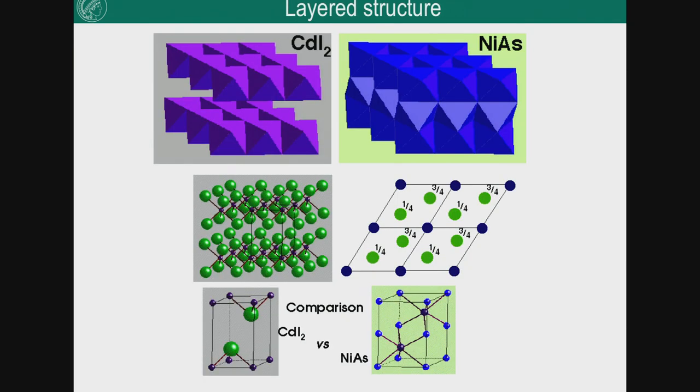So for example, I said if you have a hexagonal close packed lattice filled with all the octahedral sites with nickel, you come to the nickel arsenide structure. But if you remove one layer of nickel, so this would be Ni2As2, if we remove one layer of nickel, we come to the cadmium diiodide structure, which is related also to the MoS2 structure and all of this. You see, here we still have the cations, here we remove the cations, and here we still have the cations, so we end up with two layers of anions, and if they would be oxygen, the repulsion would be very large, because the charge concentration on a small anion is much higher than if I have a big polarizable anion. So if I have iodide, like cadmium iodide or selenide, I can remove a layer, I can have this structure.